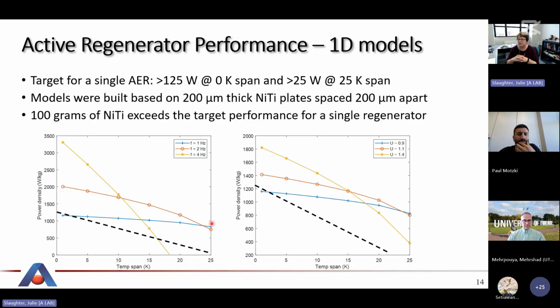So we did some active regenerator modeling. Our target for a single regenerator is 125 watts at 0 span and 25 watts at 25K span. The plate thickness we have is 200 micron, and we have a 50% porosity, so they're spaced 200 microns apart. With 100 grams of nickel titanium, we can exceed that target performance. You can see this line in both cases. This is versus different frequencies. This is a different utilization, and utilization is related to how much fluid you're flowing in each of these cycles. So in either case, we can exceed the performance that we're looking at with these 1D models.